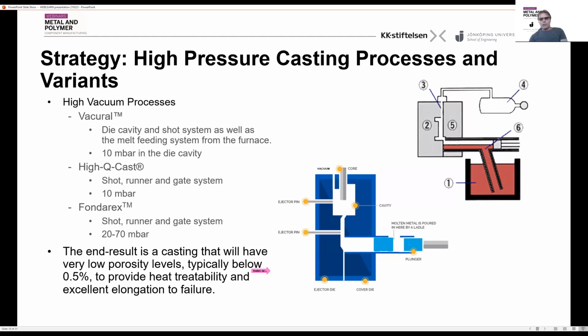Another way of dealing with all these quality issues is that when you do fill in high pressure die casting, you end up having gas in the actual die cavity, and that comes from the air. It comes from die release agent that you spray into the die chamber. And there are many very different ways of managing this. One process that has been used more lately is the Vacural process.